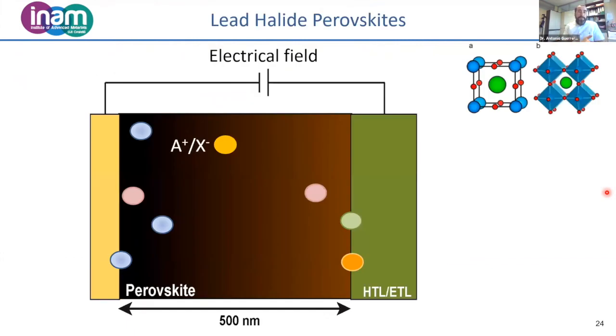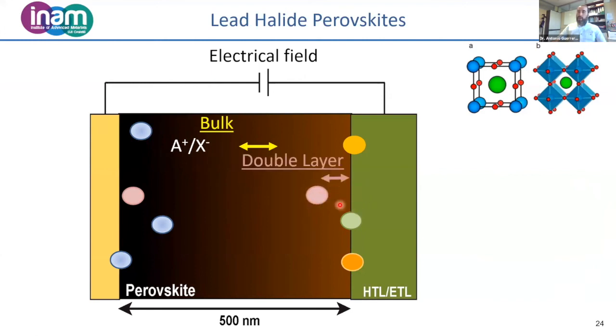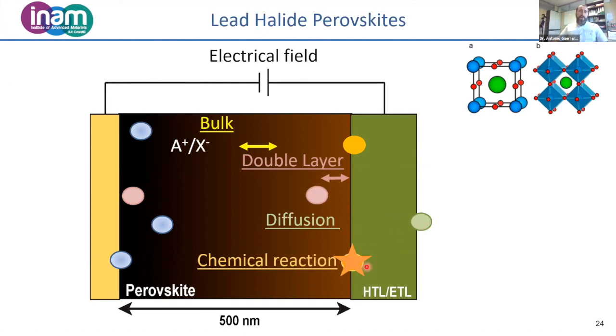So in perovskite solar cells, you followed the talks this morning and the previous talk from Uli. You know that the devices are very complex. We have electrical conductivity in the device, and by using impedance, we can try to understand the bulk properties of the material. We can try to understand the ion migration of either iodine or methylammonium. We can try to understand what happens with the ions once they are close to the contacts. These ions can diffuse from the interface across, for example, the spiro-OMeTAD. And also these ions, in the presence of an electrical field and light, can react with the contacts. All this can be detected by impedance spectroscopy. And as you can imagine, there are several processes, so the response is typically very complex.